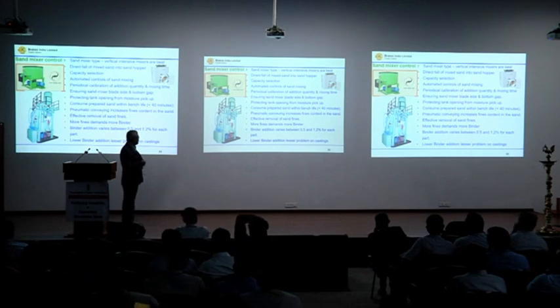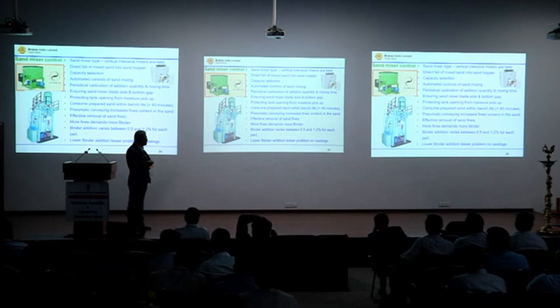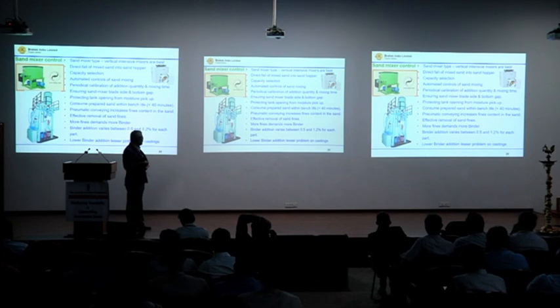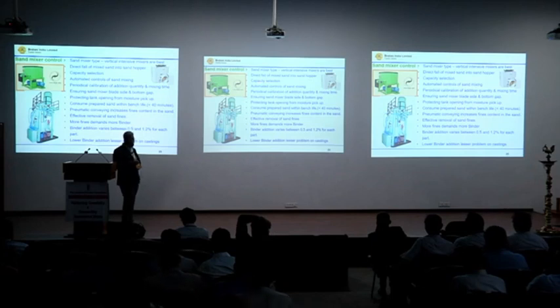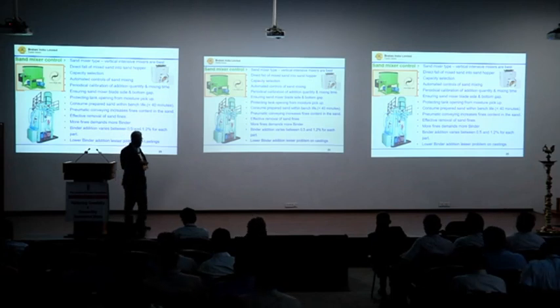This is on the mixer side, sand mixing control. Sand mixer type: vertical intensive mixers are best for cold box. Direct feed of mixed sand into the hopper is best. Capacity selection is very important based on the consumption of the sand.